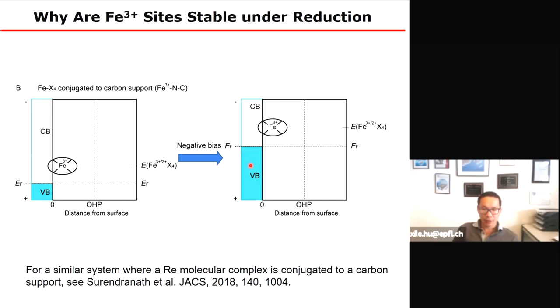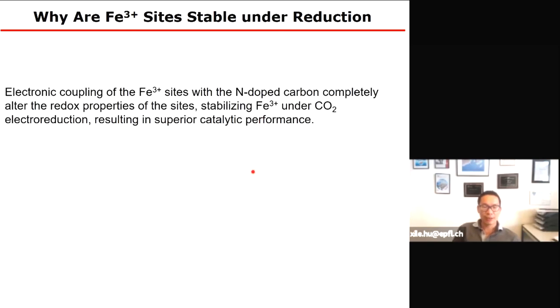And so in this case, you have a stabilized iron 3 site, and that results in this very unusual activity. This is certainly due to the cooperative catalysis, if you want, of this iron 3 site and the nitrogen doped carbon support. We think that is a case where electronic coupling of the iron sites with the support completely alters the redox property of the sites, stabilizing iron 3, and that gives you higher catalytic performance. So with this, I hope I will convince you that cooperative catalysis in heterogeneous electrocatalysis is not only mechanistically interesting, but also provides new